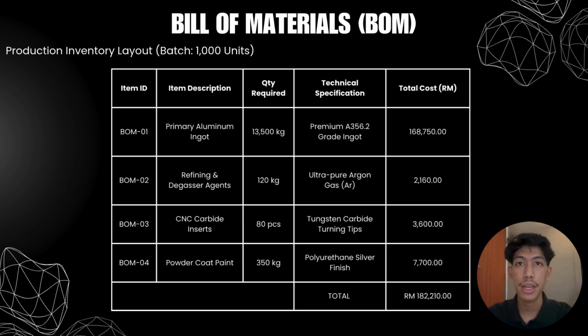To support the refining step, we budget 120 kg of ultra-pure argon gas to completely eliminate hydrogen porosity during crucible melting. We accounted for 80 carbide inserts to maintain our tight tolerance during multi-axis CNC machining, and 350 kg of polyurethane silver powder coat for ultimate environmental protection. This brings our total direct material cost to 182,210 ringgit.